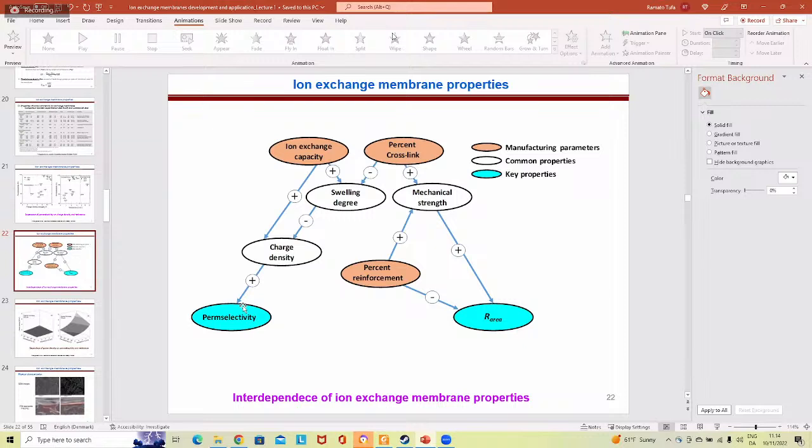If you put your membranes in potassium hydroxide for several days, the functional groups will degrade. They slowly die and disappear from the membrane. So when you ask whether we can regenerate or reuse it, this is about the lifetime of the membrane, in my understanding.